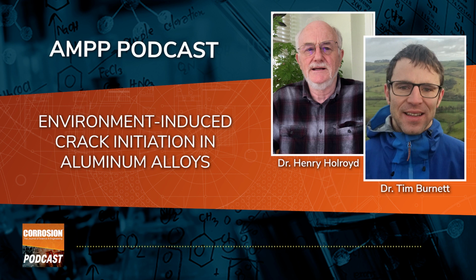So the latest characterization tools are allowing us to pull together observing microstructural changes in situ as we monitor, say, the chemistry that's evolving, and basically helping us understand those things that are building up to get this stage of initiation where we're actually forming a crack.